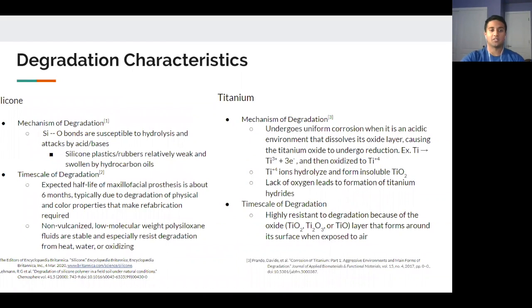In regards to degradation, silicone is susceptible to hydrolysis and attacks by its acids and bases. Silicone plastics and rubbers tend to swell when exposed to hydrocarbons, and because of their relatively weak strength, degrade as a result. Typically, the expected half-life of silicone components in maxillofacial prosthetics is about 6 months due to physical wear and loss of coloration from the body and weathering that naturally occurs. Non-vulcanized, lower molecular weight silicone prosthetics tend to be better resisting degradation from areas such as heat, water, and oxidation.